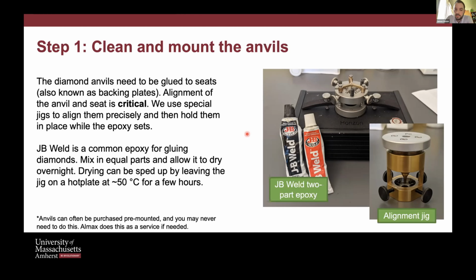And if you get this from a company, so Almax can do this. When you buy anvils and seats, they'll glue them together for you usually for a small fee, but they do a good job of that. Where it's important, especially these days, more people are moving to these Boehler-Almax type seats where the diamond sits in that conical bore of the seat itself, that there can be tilt in the diamond. So you have to check before you glue and dry everything that that's well aligned. And so we do that actually with a laser jig. This is from Almax. And I'm not getting into this, but it allows you to verify before you pin everything in place and apply the glue that the culet is flat, basically.